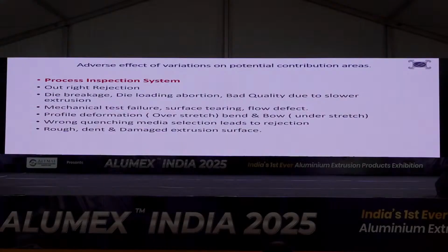So the next area is failure in mechanical test, surface corrosion on the extrusion profile. If you compromise with the potential contributing areas, you can have this problem, dirty patches, scratches everywhere. In the process inspection system, when we go there, we see outright rejection, die breakage, mechanical test failure. Profile deformation: the profile is deformed, it is cut, still it is cut up to the designated length and delivered. No one checked. Wrong quenching media selection, rough, dent and damaged extrusion surface, just pack it, load it. So if we compromise all those earlier areas shown in that cause and effect diagram, we will have this problem every day.